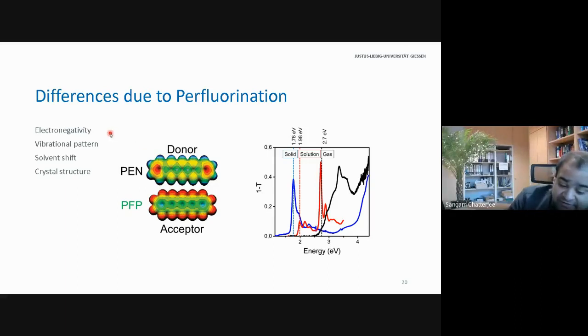Of course, the electronegativity drastically changes if you remove hydrogen and add fluorine. The vibrational pattern changes drastically. If you calculate the electron clouds in pentacene and perfluorinated pentacene, or PFP, you see that the electrons tend to be at the center of the molecule, whereas in the perfluorinated species, mainly due to the large electronegativity, the electron cloud is on the outside. It has a huge solvent shift and it has this different crystal structure.